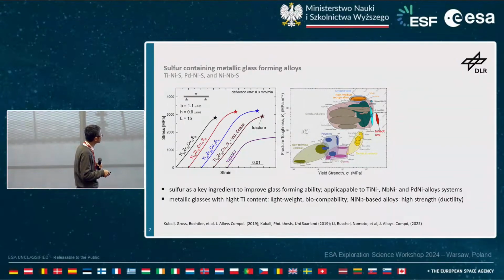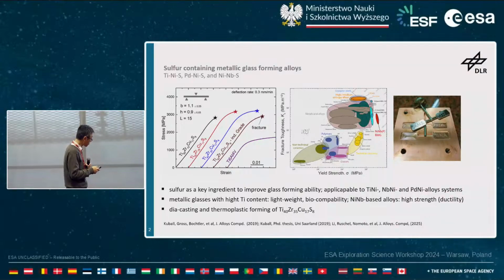So just to show you, there are some here in the engineering strengths, but in both cases, if you work with a little bit more alloy optimization, they can be cast by both die casting and thermoplastic forming, which is a special property of metallic glasses, that you can basically extrude or press them like a polymer, with which you can then cast special components.